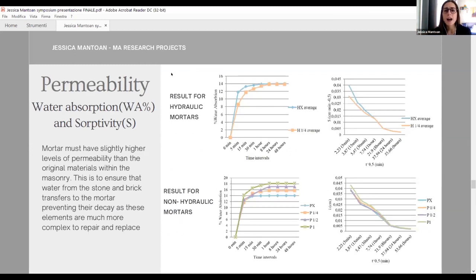Quite surprisingly, I realized that hydraulic mortar containing barium hydroxide is able to absorb less water in comparison with mortar without any additive, and that was quite surprising because from my STEM study, the surface pores were much more in mortar containing additive. But even more surprising and also more positive was the result about the sorptivity, where we can see that the orange line, so the mortar containing barium hydroxide, is able to absorb less water through the pores.